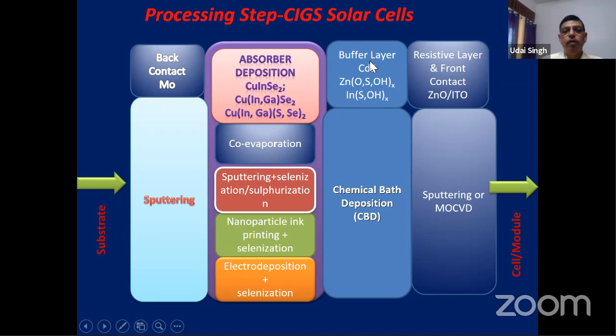Then you go for the N-type material, which is generally referred to as the buffer layer also. Cadmium sulfide is mostly used, and the Japanese use zinc hydroxide or indium hydroxide compounds. They don't want to use cadmium. On top of this, you have ITO, indium tin oxide, and/or aluminum-doped zinc oxide as a transparent conducting oxide, again deposited by sputtering, and then you can manufacture this. So this is the simple process one can follow.